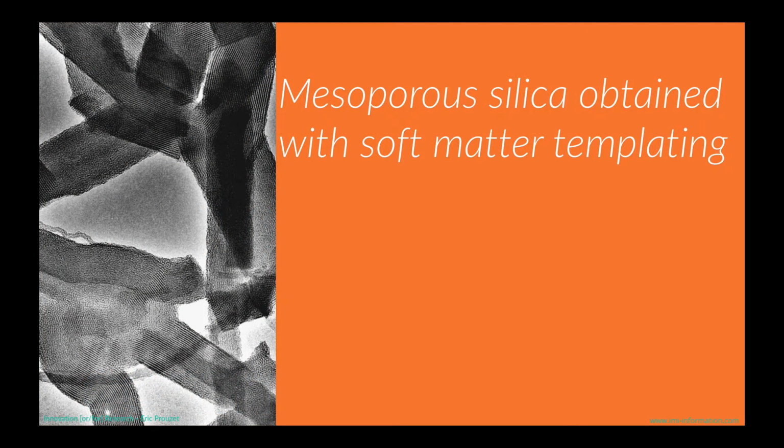I took an example of academic research leading to a new type of materials, beautiful materials. They are mesoporous silica, obtained with soft matter, the surfactants, the liquid crystals, so the soaps. And these elements of soft matter are used as template to shape the porosity of silica. On the left, you see a micrograph of porous silica where these stripes you see are actually the picture of very well aligned pores, and these pores are assembled in a hexagonal honeycomb geometry.